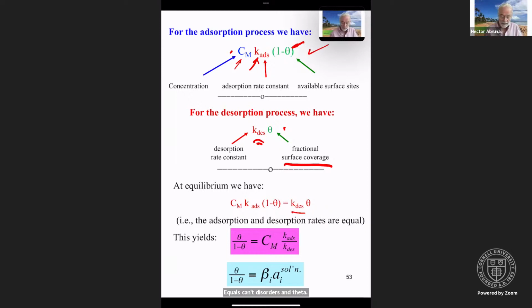We can then very simply clear and express in terms of theta. So we move 1 minus theta to this side and K desorption here. So we have that theta over 1 minus theta equals the concentration times K adsorption over K desorption, and basically this is the equilibrium expression. So we obtain the Langmuir isotherm as we saw previously. It's a very simple derivation, but it's useful for us to get a sense for how this comes. Notice that this assumes a reversible process. Very often adsorption might be irreversible, and so one has to make some sort of extra thermodynamic arguments to at least get some sense for how these things work.